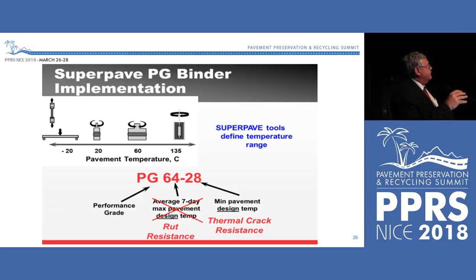And at low temperatures, originally we had bending beam rheometer and direct tension tests, but we're finding out that we can run dynamic shear rheometers now with 4mm plates and get the same low temperature information for rheology. We can run DENT tests and other things that are more convenient than the DTT to get failure strain. So the tools are changing, but we're after the same physical properties. We're just trying to make the tools easier and more reproducible so we can put them into specifications.